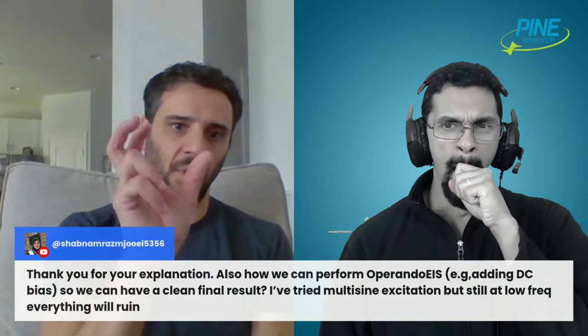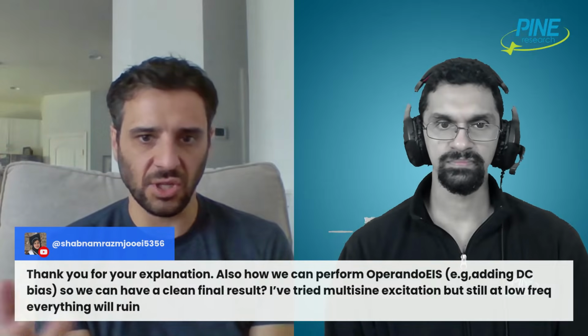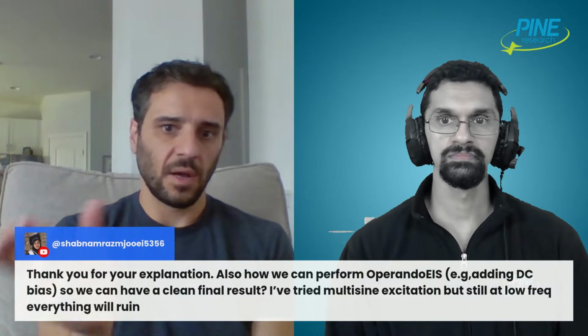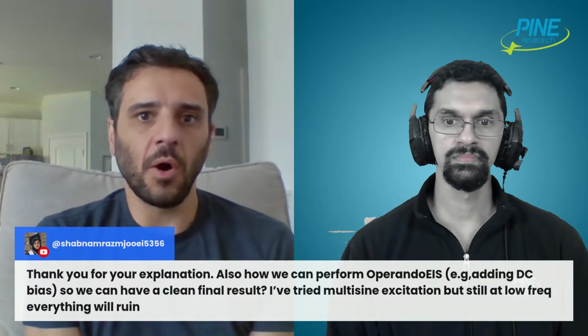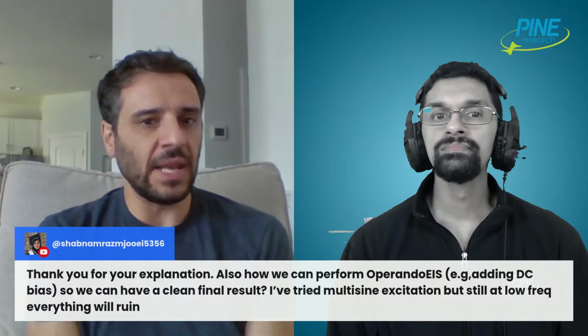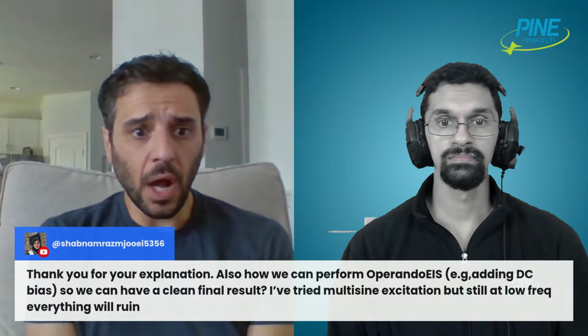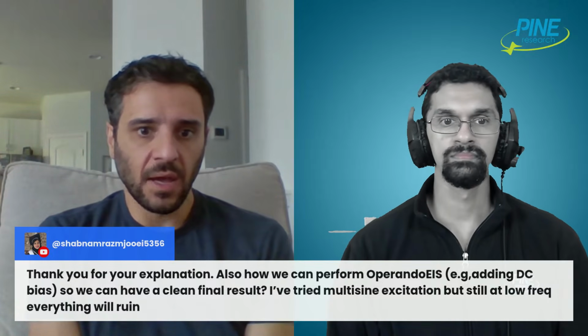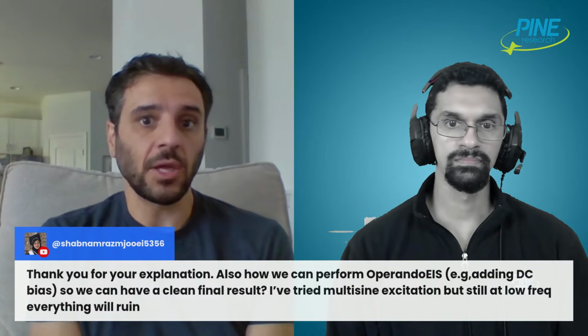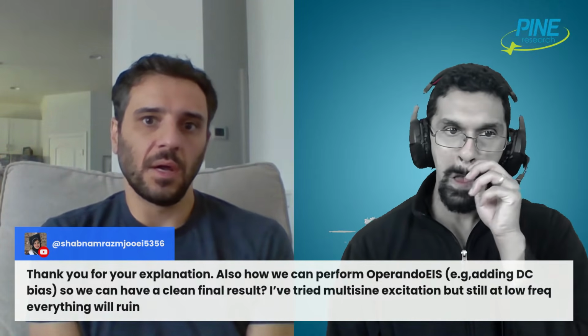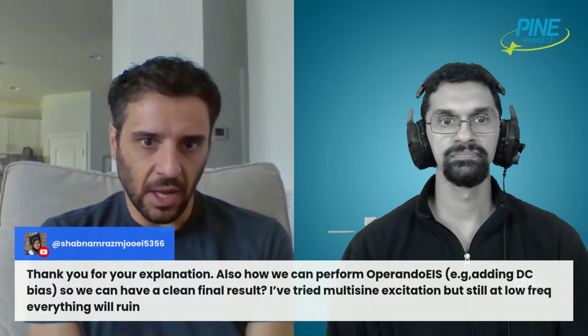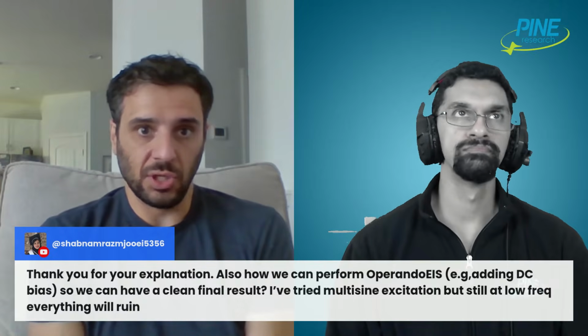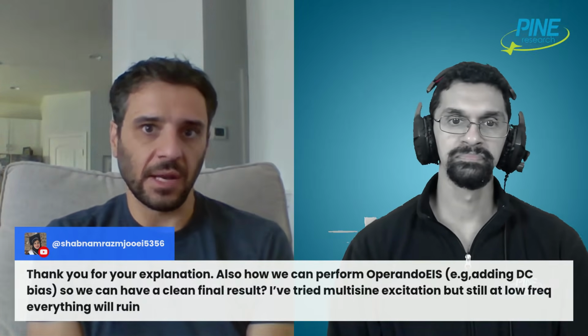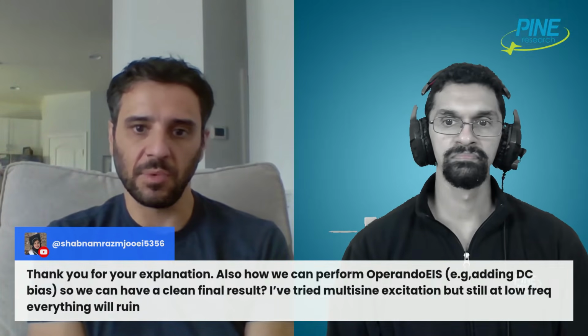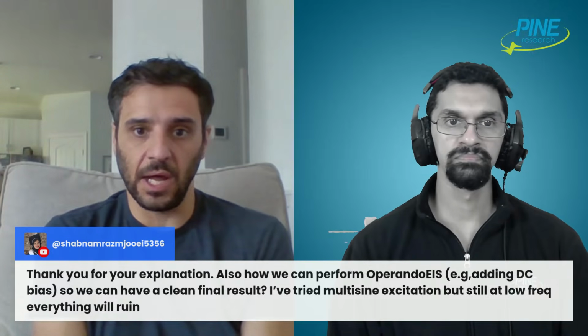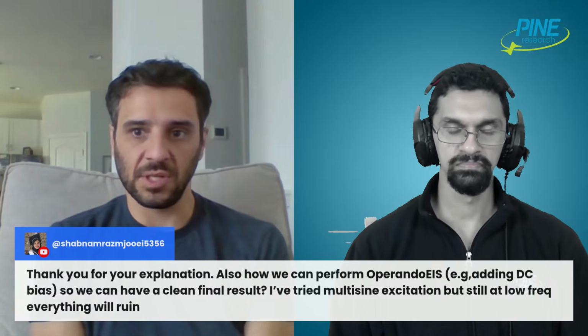And in particular, especially if you're within the like 30 to 70% state of charge, let's just say generally, the voltage is not changing tremendously under moderate load. So it's sort of stable enough, let's just say. Otherwise, though, I don't have a suggestion for you because I don't think you should be performing low frequency impedance on a battery under load. You just shouldn't. You can, but it's not impedance. It's just a sine wave, and then you can interpret that how you wish. But that's not impedance. It's just fundamentally not impedance. The signal is drifting. It's moving because your system is not stable.